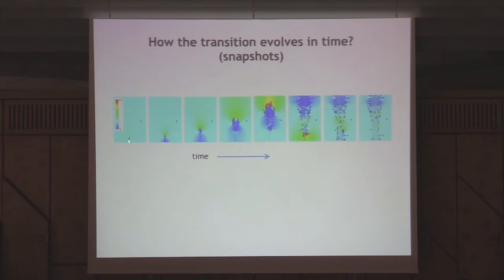I showed that at some point you have a good probability to form a segment. The moment you form a segment, you see that you have blue, now low field, because these two cells are metallic. So now you have this metallic filament. The voltage drop has to be across the rest of the system, so the electric field is enhanced at the tip of this filament. That makes the filament grow very fast, as you saw a moment ago. And you see that the field is strongly enhanced at the tip.